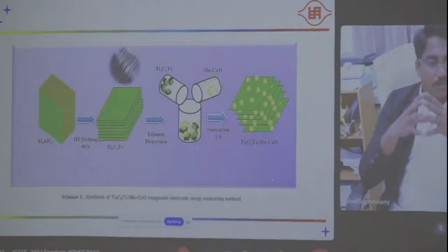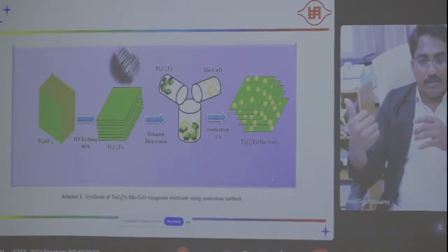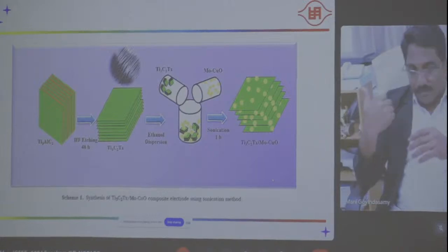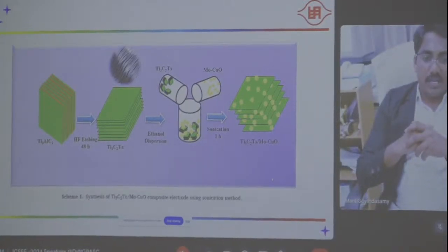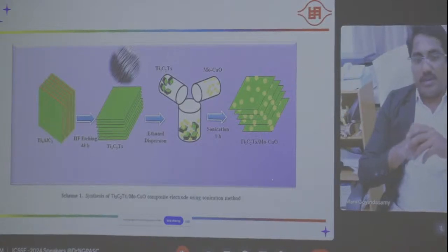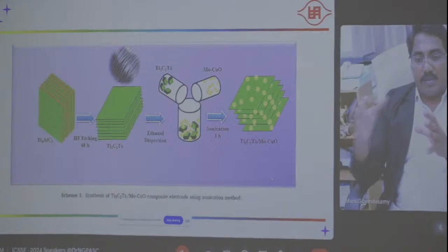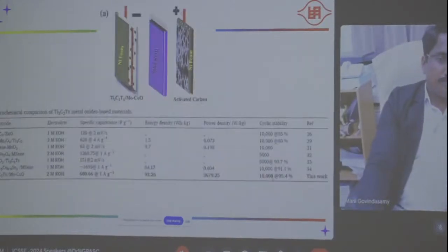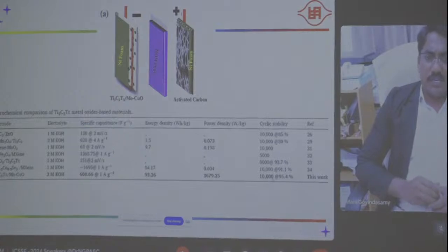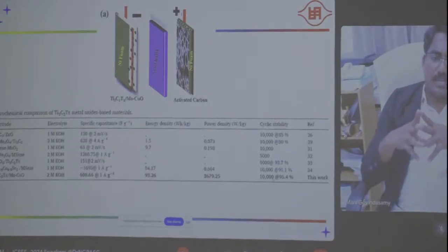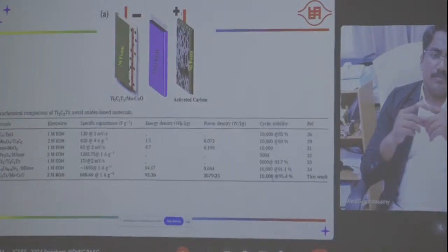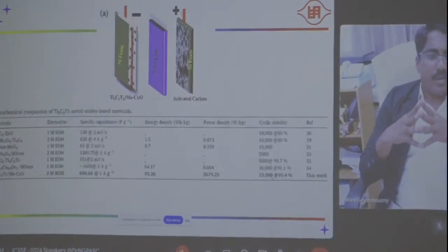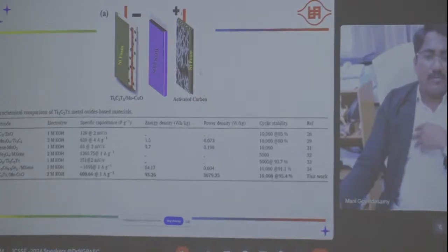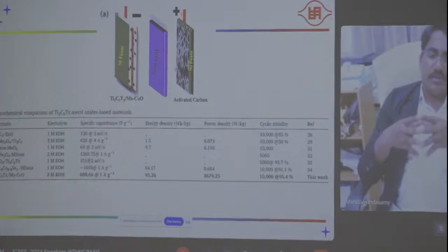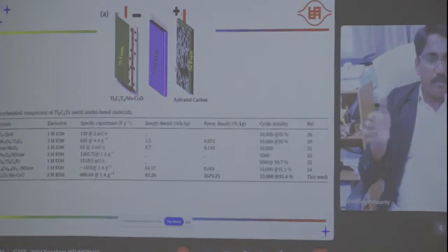So this is the synthesis procedure to prepare the bimetal oxide related MXene composites. Similar to the etching process, then we go for the hydrothermal method for molybdenum and cobalt oxide. Then we combine with the sonochemical technique to prepare the composite. In this work, we develop the device as well. Here, for the asymmetric supercapacitor, we use solid KOH as a membrane. In one electrode we use activated carbon, and in the other electrode we use the MXene related composite, that means molybdenum cobalt oxide. Then we go for device fabrication.